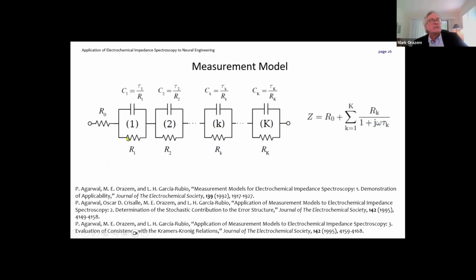Okay, the measurement model is basically a Voigt series, a series of RC elements. The print is small, I apologize for that, but we started in 1992 with our first paper on this. So we have been working on this for 3 decades, verging on 4. And the beauty of this is that the measurement model, as shown here, satisfies the Kramers-Kronig relations. So if we can fit this model to our data, the data must satisfy the Kramers-Kronig relations too. It is relatively easy to fit, and it will account for different kinds of behaviors, including inductive features.